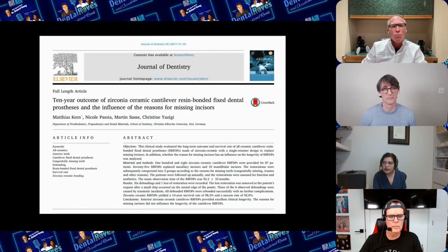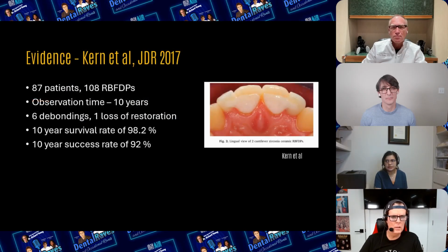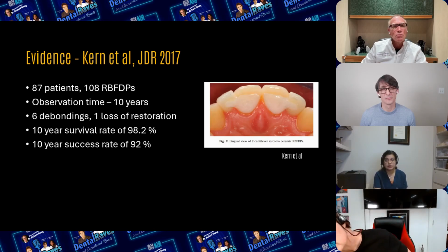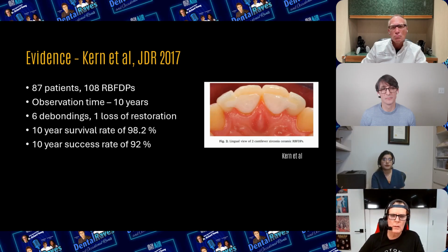Okay. Then deep diving into this paper, which is a 10-year outcome of zirconia ceramic cantilever resin bonded fixed dental prostheses with single wing, and the influence of the reasons for missing incisors. We are not interested in the reasons of the missing incisors, but we are interested in the 10-year outcomes. So this is probably the best you can get in terms of a long-term clinical evidence paper for zirconia, believe it or not. This paper is based off of 87 patients and 108 RBFDPs, all single-winged. Observation time was 10 years. 6 debondings and 1 loss of restoration was observed. And so this paper concluded the 10-year survival rate of 98.2% and 10-year success rate of 92%, which is pretty great.